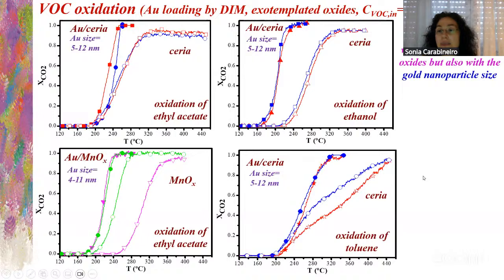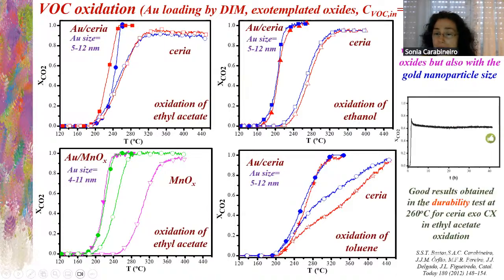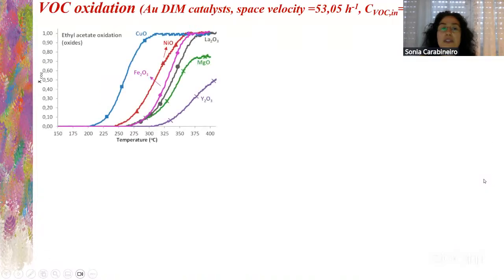And we see that the activity is related with the reducibility of the oxides, but also with gold nanoparticle size, because here, manganese oxide is more reducible than cerium oxide, okay? And the gold nanoparticle size is also smaller. And we also obtained good results with the durability test, okay? Here, for this cerium material, okay? See, it's up to 40 hours, it is very good.